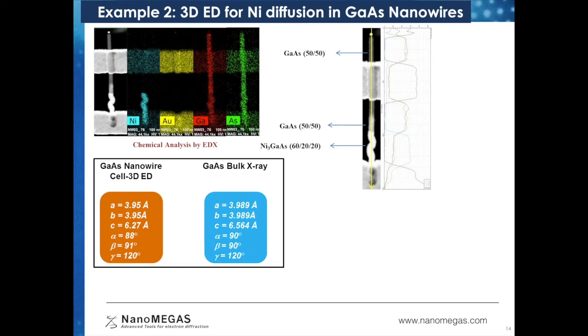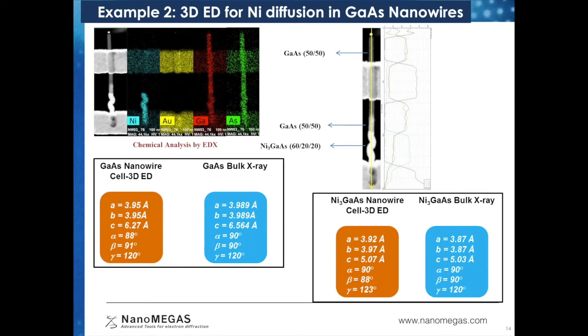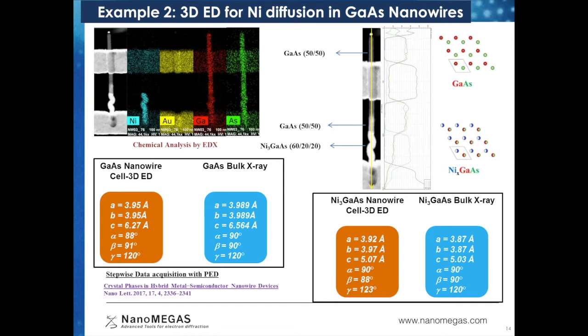3D electron diffraction data was acquired in stepwise mode with precession, and the unit cell was determined, and the obtained unit cell from these 2 different locations matches well with the X-ray result from the bulk material. Then from this 3D ED data, it was also possible to solve the structures of these 2 different phases. In this case, the electron diffraction data acquisition was done in stepwise mode with beam precession. The reason to do it in stepwise mode is that the crystal size was very small, and it was very difficult to track the crystals during the tilting procedure.